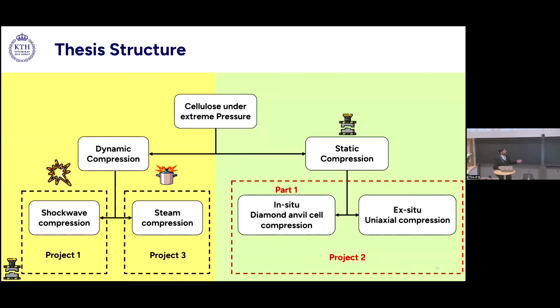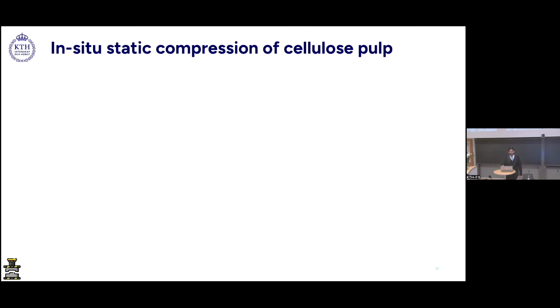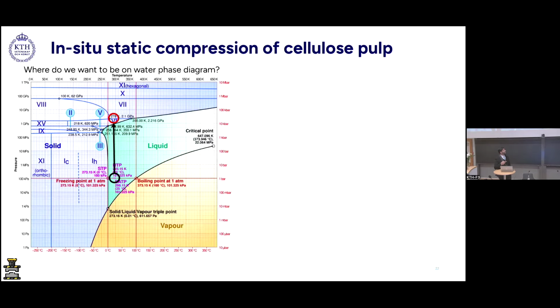So let's start with part 1, which is the in-situ static compression. In the water phase diagram, we started at room temperature again, and we wanted to go all the way into the crystalline ice form. If you start compressing the water at roughly 1 gigapascal of pressure at room temperature, you will hit the ice 6 region, so the water will rearrange itself in compressed ice form. If you keep on compressing at roughly 2 gigapascals of pressure, you will hit the ice 7. At 1.8, 1.81 gigapascals of pressure, ice 7 crystals will start to appear in a metastable form. They will not be stable crystals, of course, but they will get stable at roughly 2 gigapascal pressure.